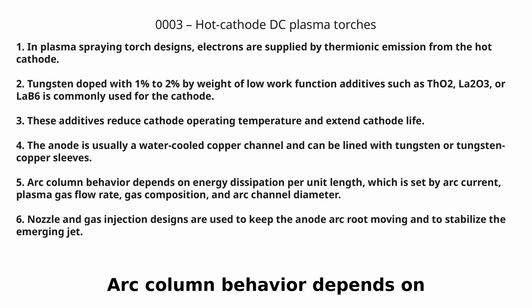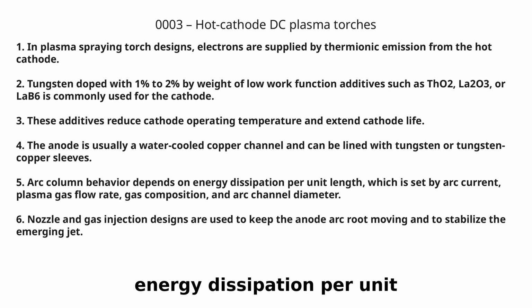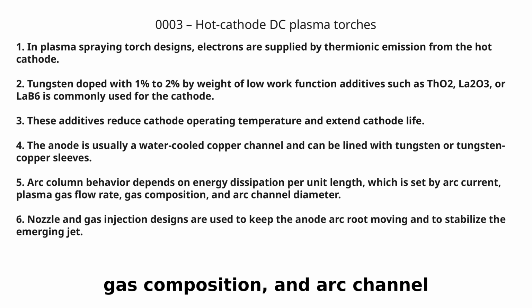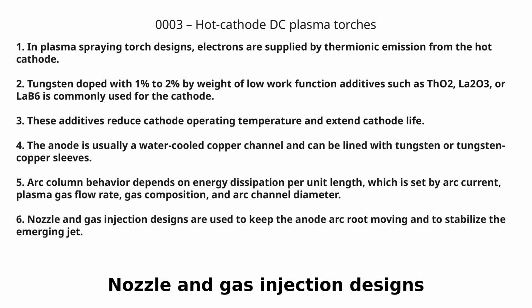The anode is usually a water-cooled copper channel and can be lined with tungsten or tungsten copper sleeves. Arc column behavior depends on energy dissipation per unit length, which is set by arc current, plasma gas flow rate, gas composition, and arc channel diameter.